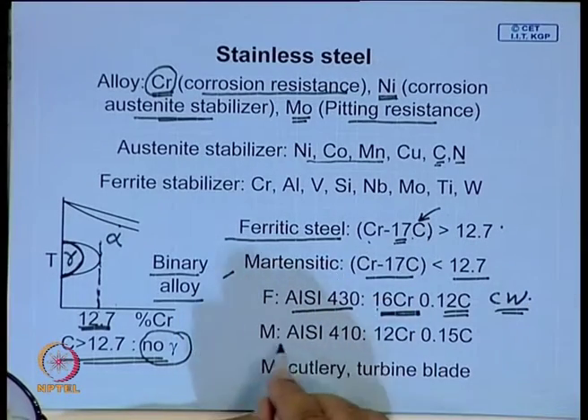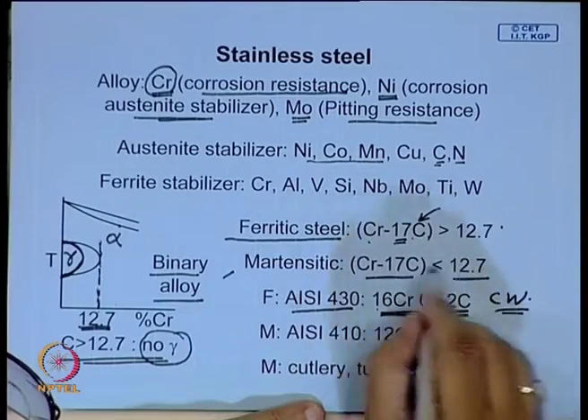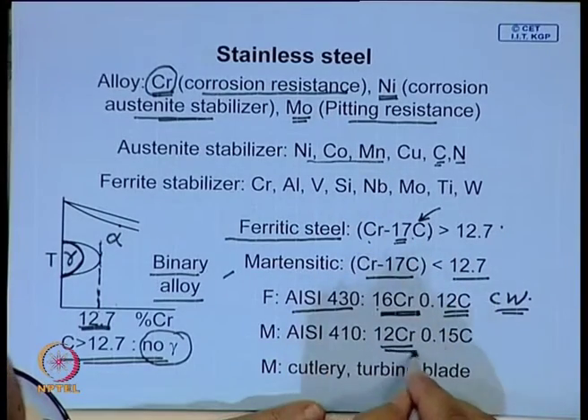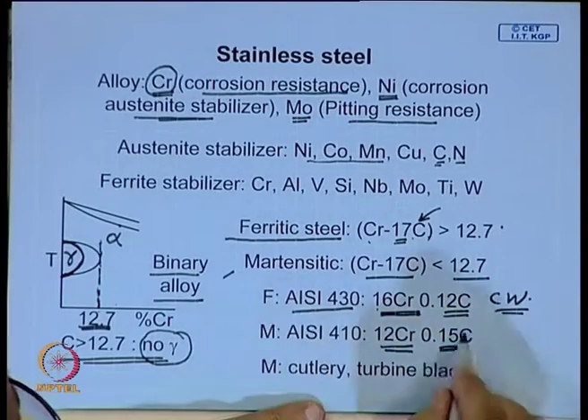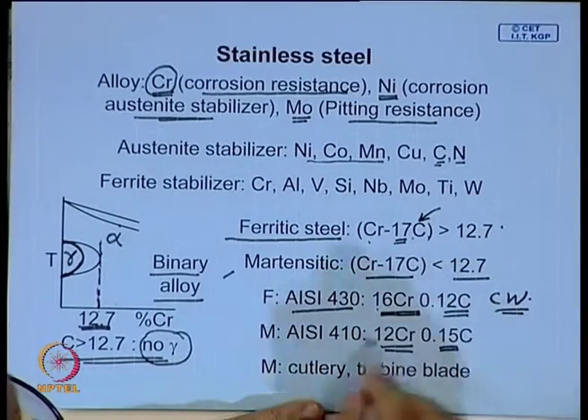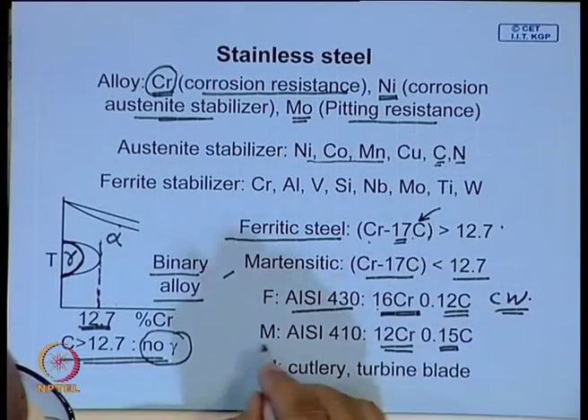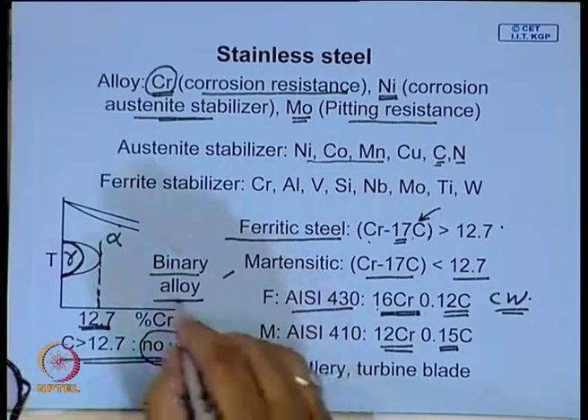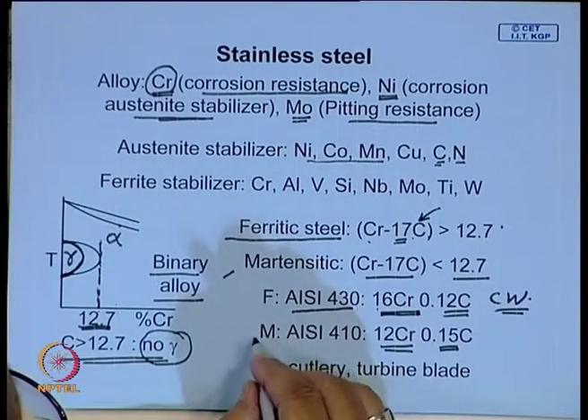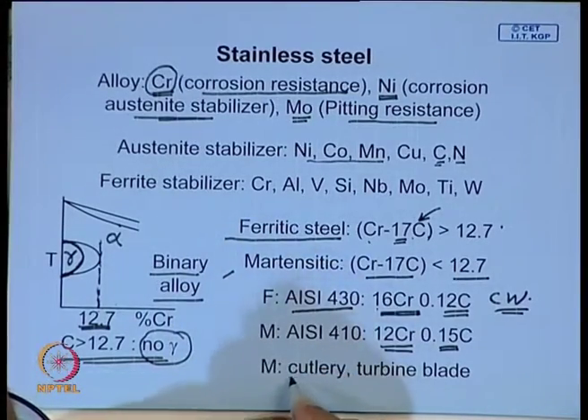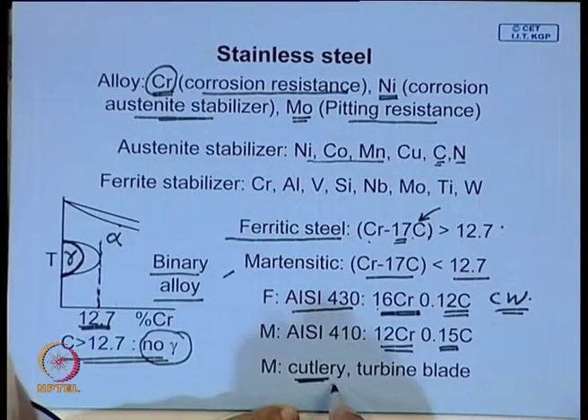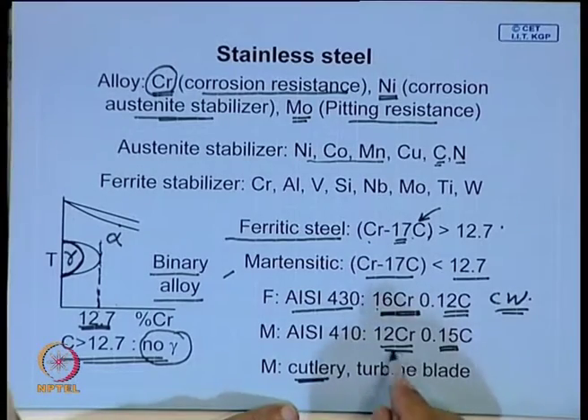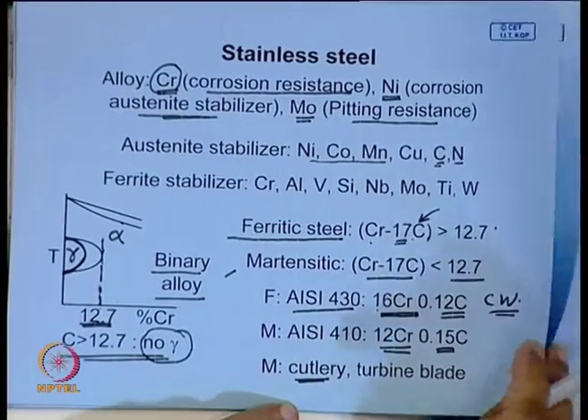Whereas, if you have, in this particular case, 12 chrome, 0.15 carbon grade, this is a martensitic grade stainless steel. It can be heated to the austenitic region, and on quenching you get martensite. So, this is a steel commonly used for cutlery. Some of the turbine blades in engine turbines are also made up of this type of steel.